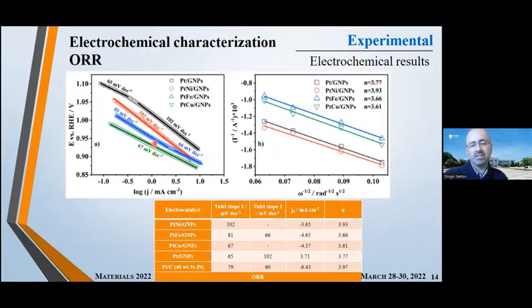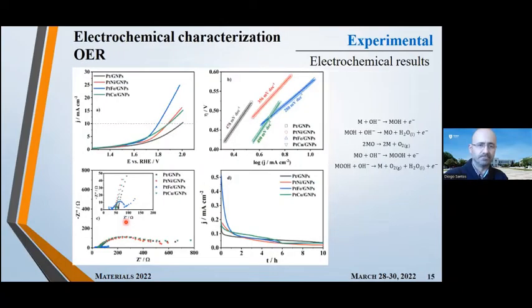Also, we determined what is known as the Tafel slope, also from the curves for the oxygen reduction reaction that I just showed. So here on this table, we have a comparison of different parameters that we calculated, also including the diffusion limited current density that was also higher for the platinum iron supported on the graphene nanoplatelets. So this platinum iron for oxygen reduction was the most promising material.